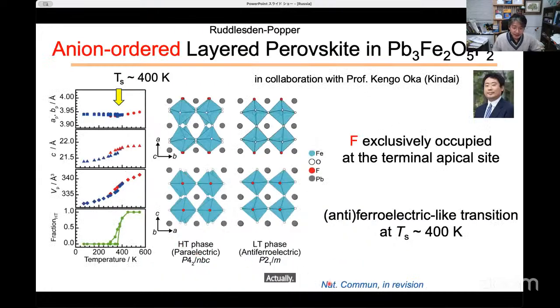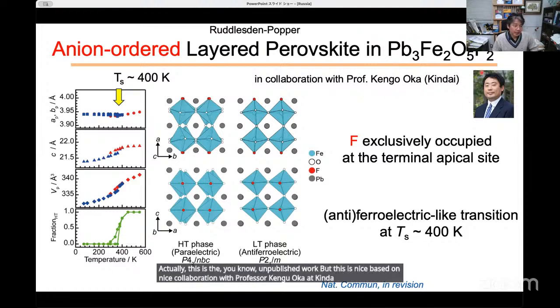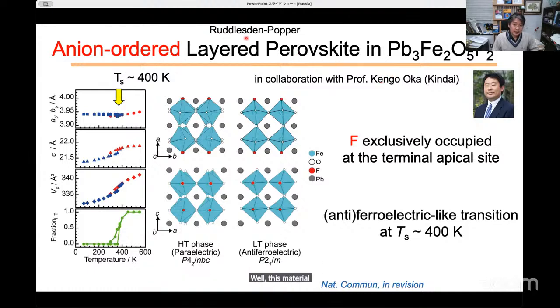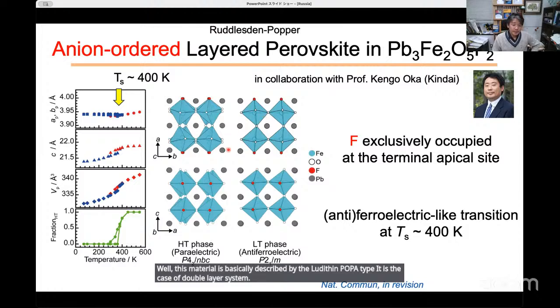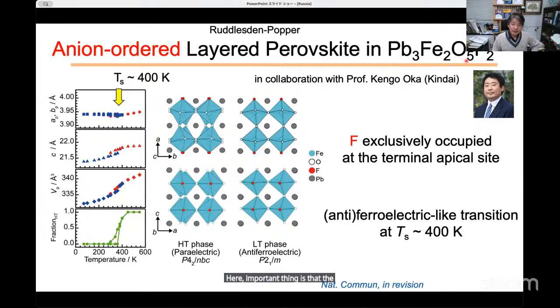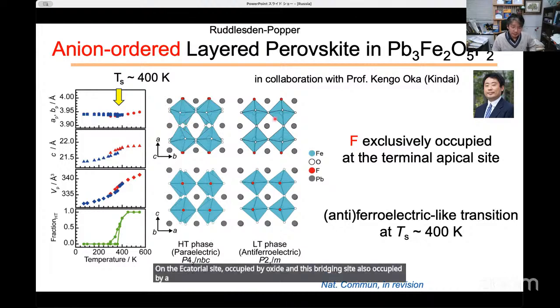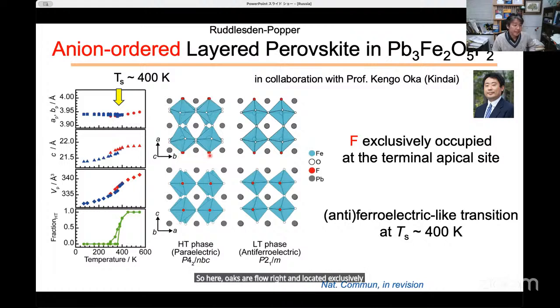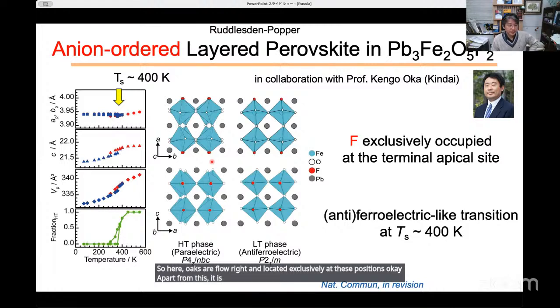This is unpublished work, based on a nice collaboration with Professor Kengo Oka at Kindai University, who made these new materials. This material is basically described by the Ruddlesden-Popper type layered perovskite, in this case a double-layer system. The important thing is that oxide and fluoride are ordered, not disordered. The fluoride, shown in red, is located preferentially at the apical site. The equatorial sites are occupied by oxide, and the bridging site is also occupied by oxide anions. So fluoride is located exclusively at these positions. Apart from this, it is a simple Ruddlesden-Popper type perovskite.